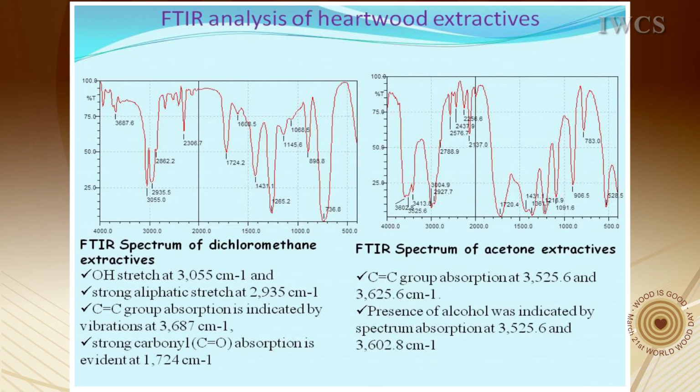That one is a representation of what my professor sent me after analyzing the compounds. He told me that most of those peaks showed that the extractives had a lot of aliphatic compounds, carboxylic acids, ketones, and other phenolic compounds, and these have been associated with inhibiting attack by fungi, even from literature.